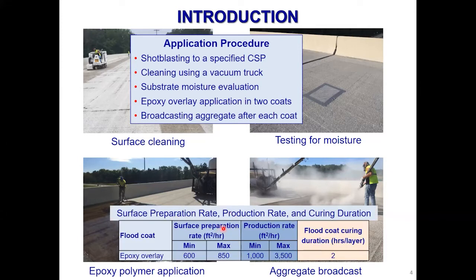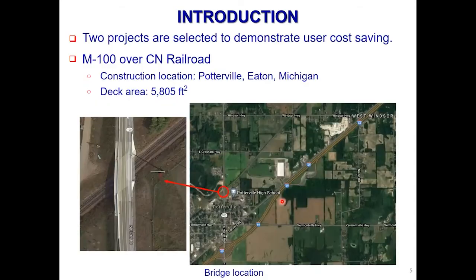So typical rates of what we call the surface preparation and production rate, we need at least like 1 hour. We can clean about 600 to 850 square feet. When we apply overlays, within an hour, we can apply about 1,000 to 3,500 square foot per hour. But we need 2 hours at least as the curing period between each overlay. So if we look at a typical project, this will require at least 2 days, depending on the size of the bridge deck.